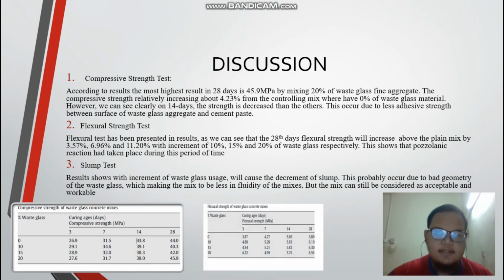Next is the flexural strength test. As we can see in the results, the 28-day flexural strength increased above the plain mix by 3.57%, 6.96% and 11.20% with increments of 10%, 15% and 20% of waste glass respectively. This shows that a pozzolanic reaction had taken place during this period. For the slump test, although the increase in waste glass causes a decrease in slump, the mix is still considered workable.